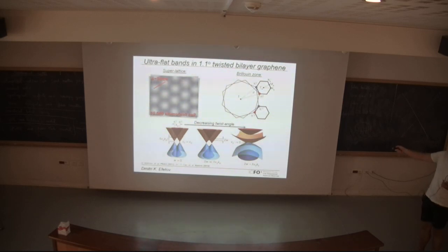Each of the top and bottom layers independently has a single Dirac cone, and if we rotate the layers close to one another, then the Dirac cones in K space are separated by this distance, which is v0 times K theta. This is what's shown here. For any arbitrary angle, if we start with a twist angle of 15 degrees, experiments were done on this, and you really end up with two Dirac cones, and the two lattices are just separate. So you really don't have bilayer graphene, but two layers of graphene independently sitting on top of one another. Things only become interesting when this distance shrinks, when these band structures become very close to one another, and then they begin to hybridize, as is demonstrated here.